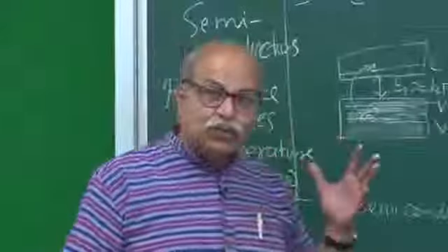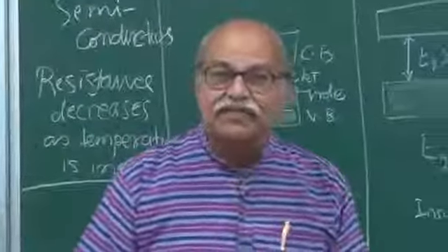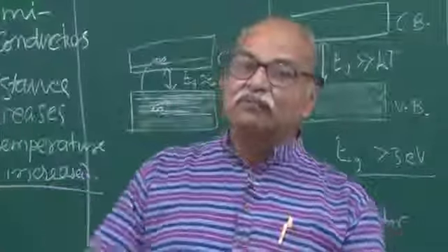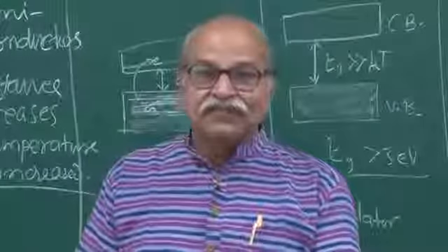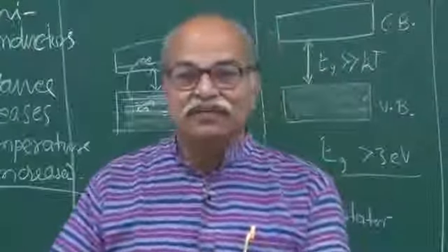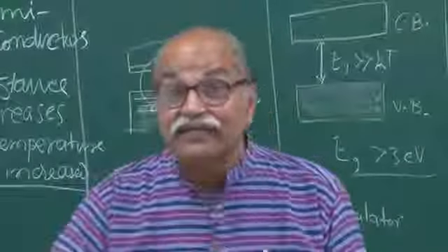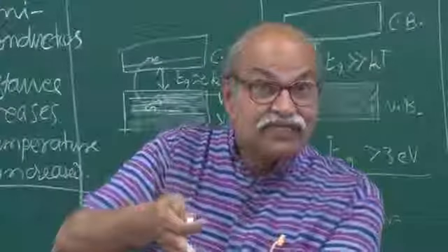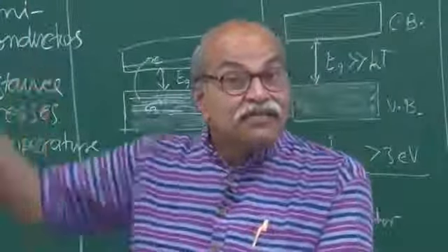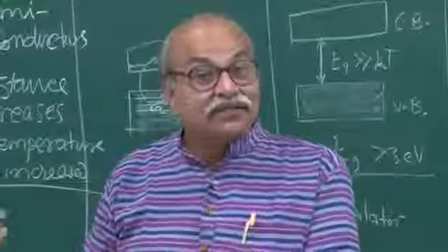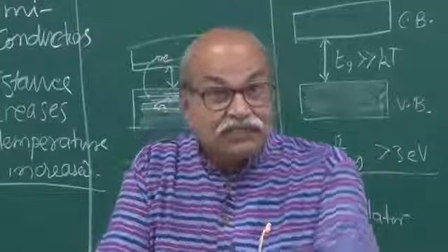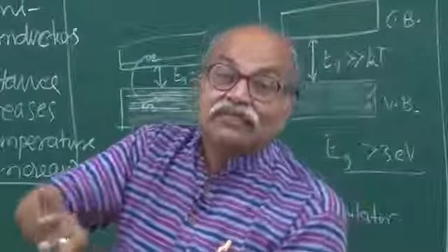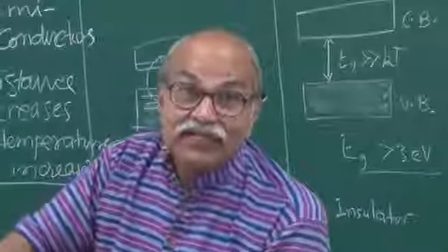This can be used to identify experimentally which material is a conductor and which is a semiconductor, or if in some process there is a transition from metal to semiconductor or metal to insulator. If there is some kind of transition, it can be identified experimentally by looking at the temperature dependence of the resistivity, and you can identify when the material was in the conducting zone, and when it becomes semiconducting or insulating.